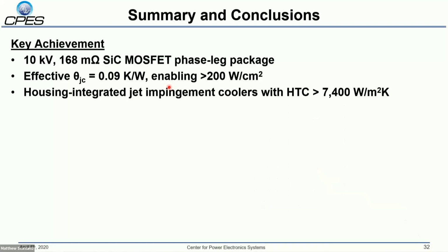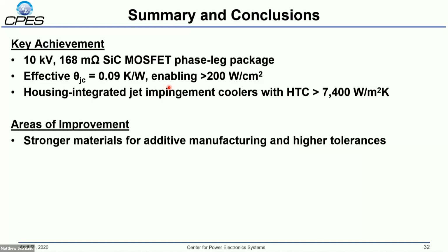So with that, I'll wrap it up. Some key achievements here is that we've demonstrated a 10 kV, 168 milliohm silicon carbide MOSFET package. We've got an effective theta JC of about 0.09 K per watt. So that's that junction to case component. The junction to ambient with the cooler is about 0.44 K per watt. If we get that HTC a little bit higher with the higher flow rates, theoretically, we should be able to support about 200 watt per centimeter squared over that experimental theta JC. And so at that 0.6 LPM that we looked at, the housing integrated jet-impingement coolers achieve an effective HTC of a little over 7,000 watt per meter squared Kelvin.